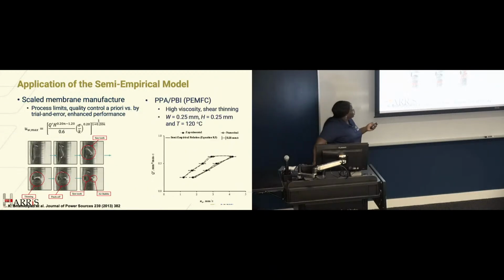And we applied this to some membranes. This is the high temperature membrane here, and as you can see, it actually has a cap, because what we found is that this material is highly viscous. Unless we applied heat, we were not going to be able to reduce the viscosity, but our goal was to not use heat and make it as sustainable as possible and not add any more energy or cost to the manufacturing process. But that means we're limited in space. The good thing is that our predictions were very accurate, within 5% accuracy, by applying the model to the experimental data.